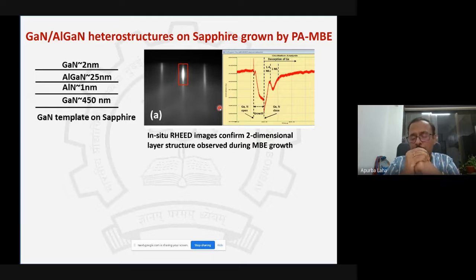The interesting thing is that when a gallium atom comes onto the substrate, we call it a gallium adatom, and a nitrogen atom coming onto the substrate, we call a nitrogen adatom. Now, in order to form a two-dimensional crystal with the best possible periodicity or ordering, these adatoms need to move around on the surface in order to find their lowest energy positions, right?